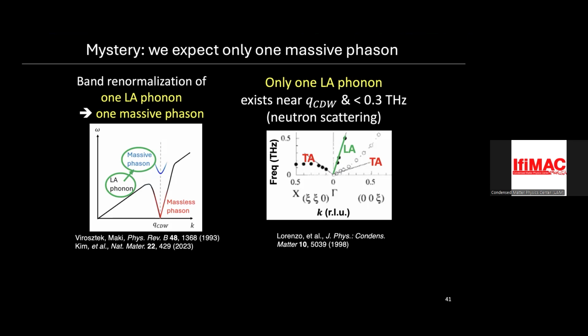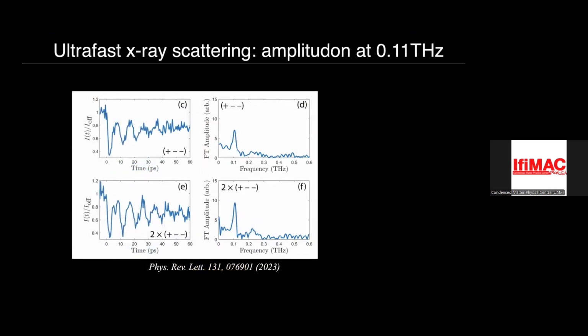Okay, so what about the amplitude mode? Now, there's no reason to expect that the amplitude mode should be half the phase mode, but maybe it is. And in fact, X-ray studies, this is time-resolved X-ray. Someone here wants to do time-resolved X-ray. If you sit on top of a charge density wave peak in X-ray, you can watch how it oscillates as a function of time. It's the same experiment we're doing. You pump it with some pulse light, and you watch the oscillations of the CDW peak. You see that it oscillates at a frequency of 0.11 terahertz. So this group suggests that there's an amplitude mode at 0.11 terahertz.